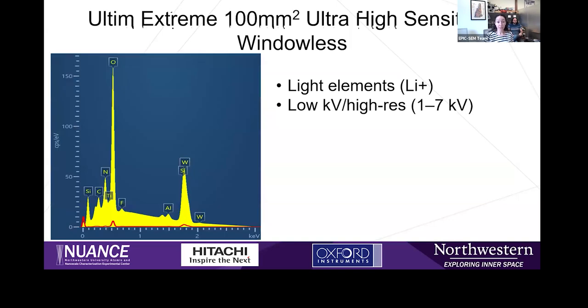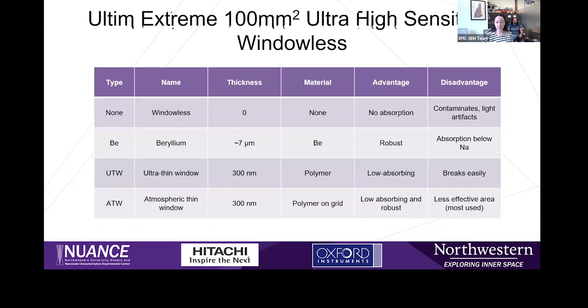Just to give a comparison with an Ultim Max detector, which is also very sensitive, you can see that in the low kV range, this Ultim Extreme detector is even more sensitive for those light elements. You can really see the difference here where the red is showing a spectrum from the Ultim Max instead, and then in yellow you have the Ultim Extreme. So really good for low kV and light elements.